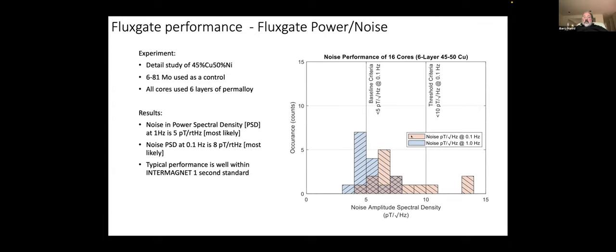The pink histogram shows the data for the 0.1 hertz, and the blue histogram shows the data for 1 hertz. And you can see that a typical noise at 1 hertz for one of these racetrack sensors is about 5 picotesla, and typical noise for 0.1 hertz is about 7 or 8 picotesla. And I should note, these are for a single sensor core, each core 35 millimeters long, or 30 millimeters long for the actual core material.